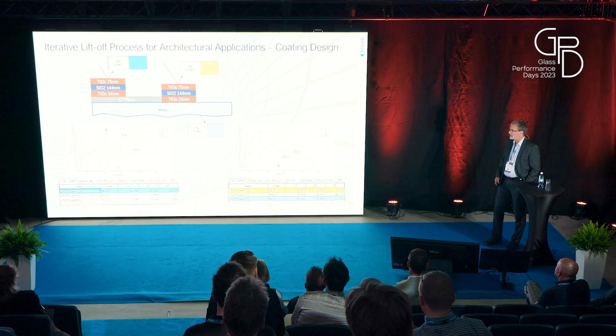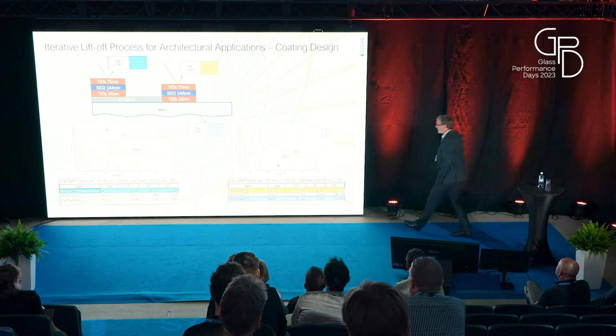In the second area here, we actually have a transmission color and a reflective color, with a dielectric coating sitting directly on the glass. We achieve a very greenish, very yellowish color in reflectance, very distinct. And in transmission, because we have no absorption, you find the complementary color, which is blue. We have a little bit of difference in absorption, as you can see here, which is due to the raw glass absorption that plays a role here.